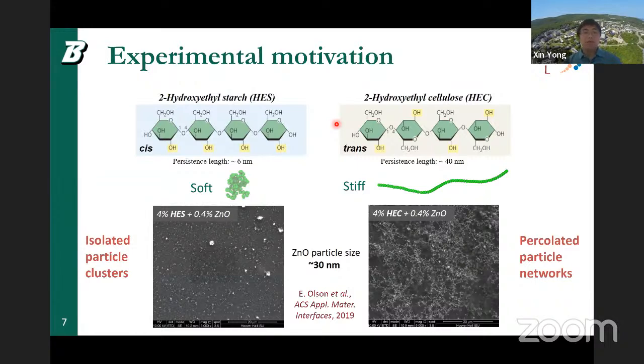So one important, interesting finding they found is that despite the similarity of these two polymers, as we can see here from their chemical structure, they are essentially the same polymers chemically-wise. The only difference is that the positions of the hydroxyl groups are different. That will lead to different conformations and their bulk properties being very different. So starch is more like an amorphous polymer, while the cellulose has more ordered